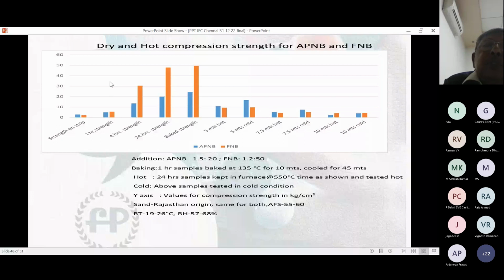Usually, inorganic binders, mainly sodium silicate, have very good hot strength, but the dry strength is lower, so binder addition has to be increased to increase the dry strength, which eventually increases hot strength also. So that is the disadvantage. And Alphaset, being a combination of inorganic and organic, gives a compromised formula for dry and hot strength. This is a strength and weakness.